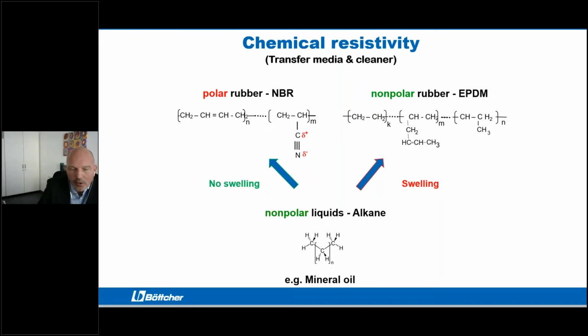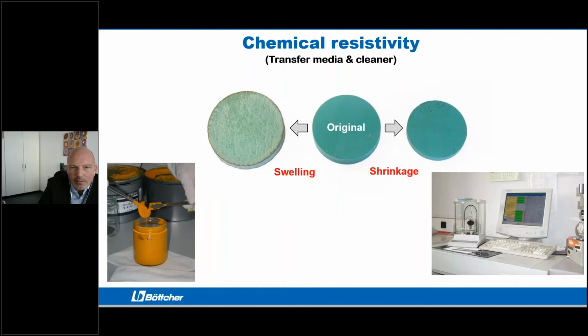And same in the opposite, if you have a mineral oil-based product, which is used, for example, as an ink for offset, and you have a polar rubber, then you have no swelling. If you combine mineral oil with an EPDM, then you will see swelling. Swelling means increase of volume and decrease of hardness. Shrinkage means a decrease of volume and an increase of hardness.